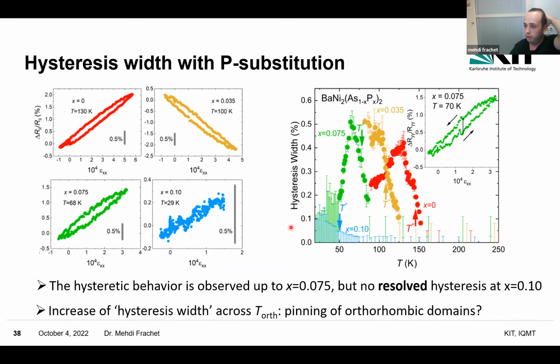And to do that, we plot the hysteresis width, which is defined like that. So that's the maximum width of the resistance versus strain variation you see at a given strain. And so that's the definition, the way to quantify this hysteretic behavior, which was also used in the strontium doped sample. So what you can see is that we observe a strong enhancement of this hysteresis width across the T star temperature, the maximum of elastoresistance, up to 7.5%.